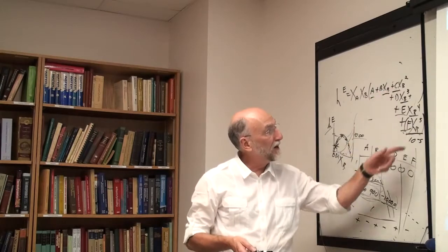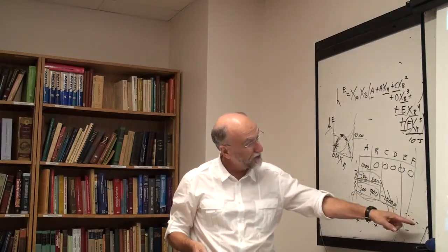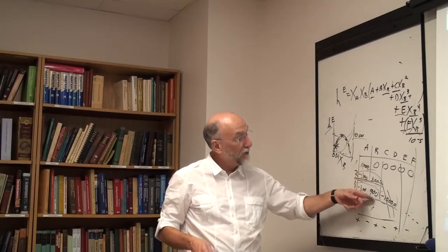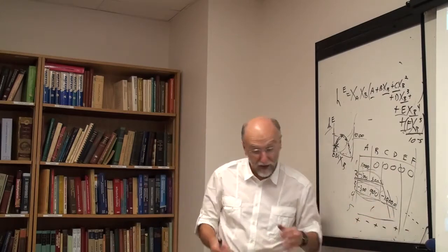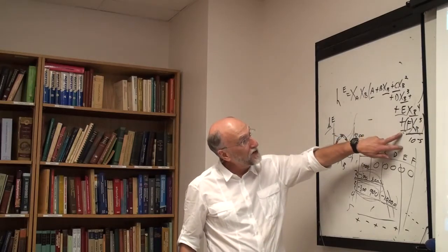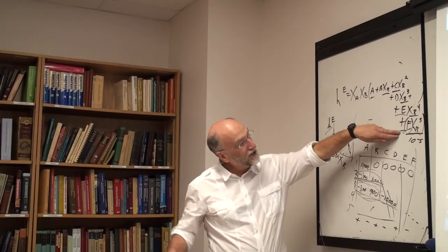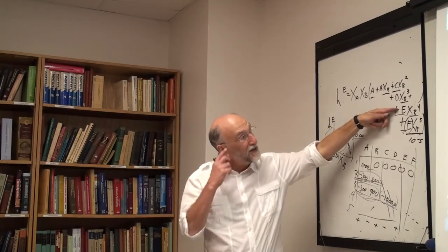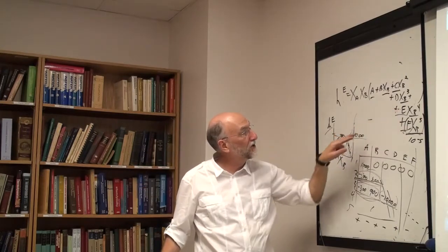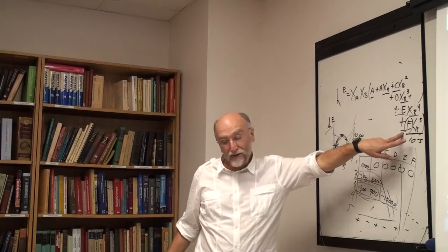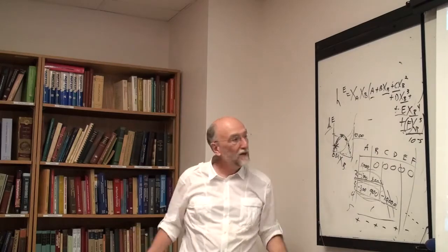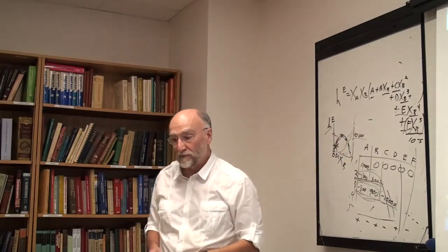So if you use a standard power series, you're going to find your terms getting bigger and bigger, and the signs alternating. The actual numerical values don't remain constant, and you have to maintain large numbers of significant digits because you're taking the difference. As I say, if f is 10 to the 6th times something, and e is 10 to the 6th times minus something else, it's the difference that's important, and therefore you've got to maintain it out to 7 or 8 digits in order that it's accurate to 10 joules, because the coefficients themselves are on the order of 10 million joules. So that's the problem with using straight power series.